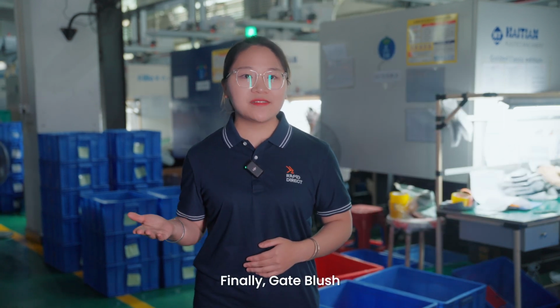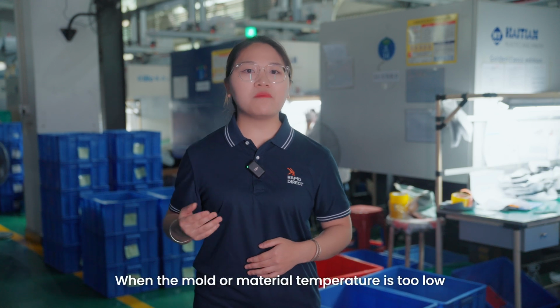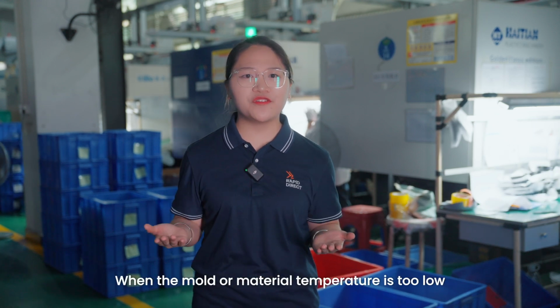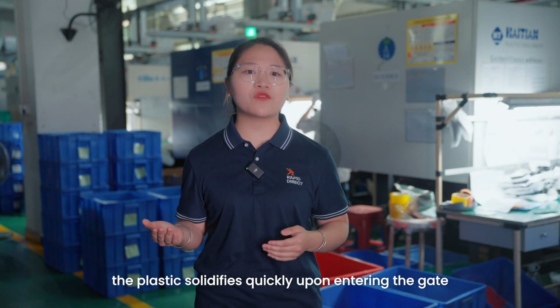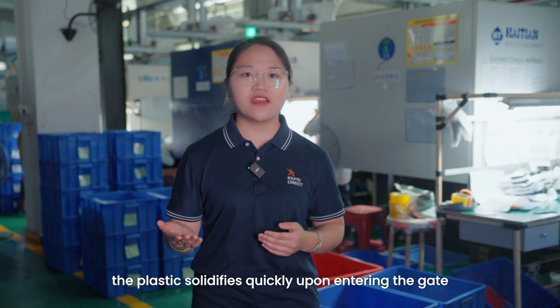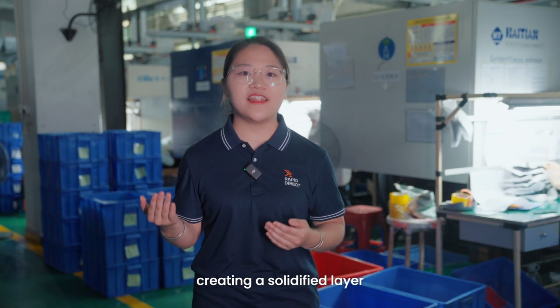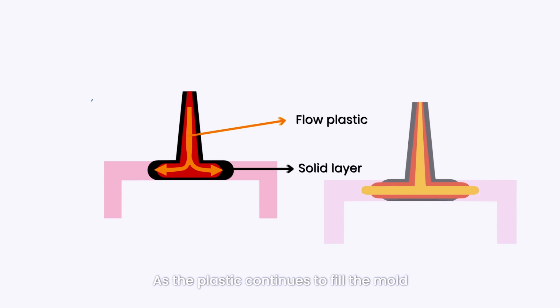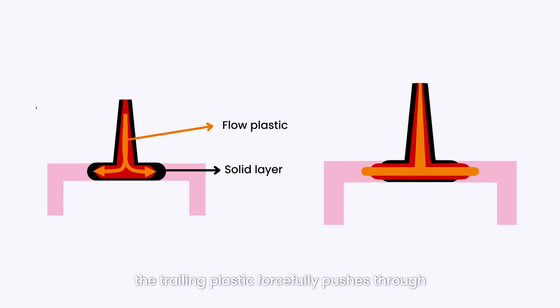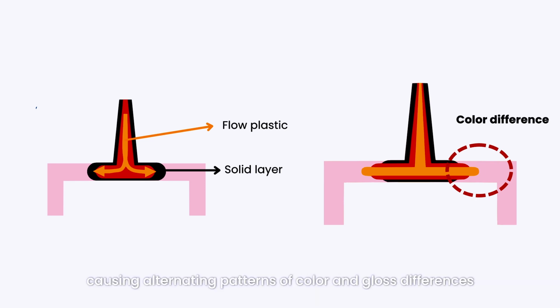Finally, gate blush. When the mold or material temperature is too low, the plastic solidifies quickly upon entering the gate, creating a solidified layer. As the plastic continues to fill the mold, the trailing plastic pushes through the already solidified layer, causing alternating patterns of color and gloss differences.